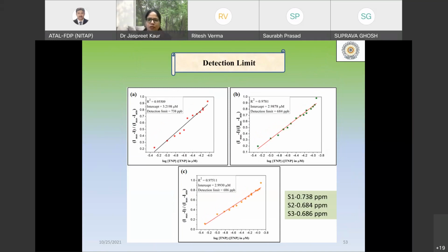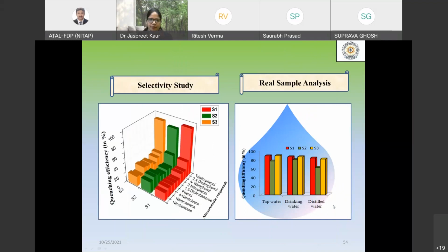So this is the detection limit. This is again the detection limit for the detection of TNP in 90% aqueous and DMSO medium. So it shows a very low, good detection limit in parts per million. And this is the selectivity study. The other nitro compounds have been compared, like trinitrophenol. All the samples show different sensitivity for the compounds, but the sensing for trinitrophenol was the highest. The real sample analysis was also done by spiking tap water, drinking water, or distilled water, and the real samples also show good results.